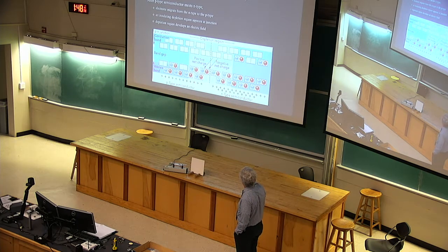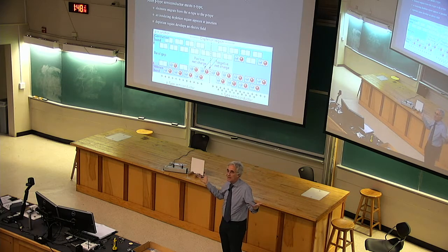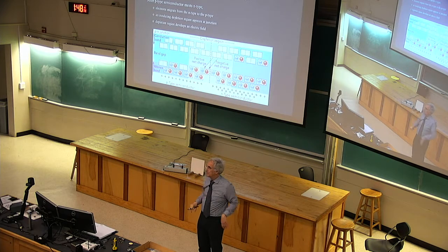All the conduction levels are empty and the valence levels are full, by virtue of this migration and settling. And this is called the depletion region. It's an insulator again. It doesn't carry electric current. That PN junction loses its ability to conduct electricity right there in that central region.